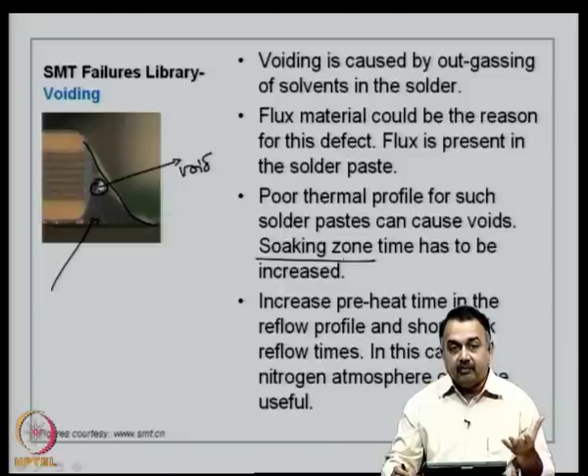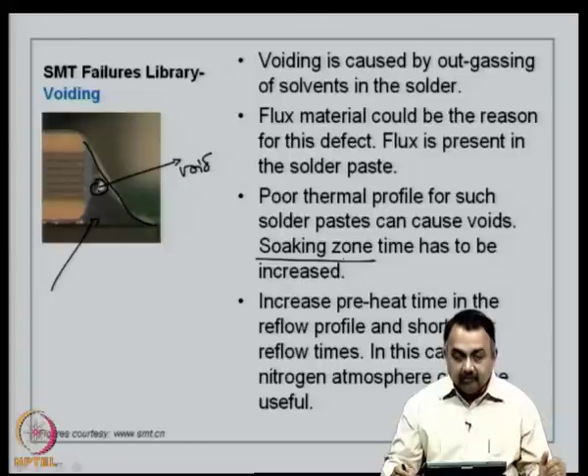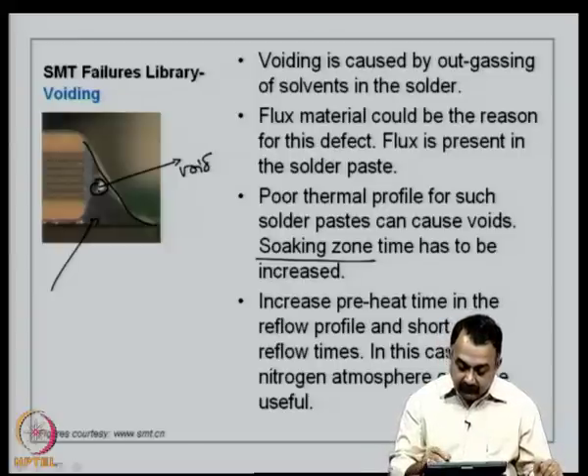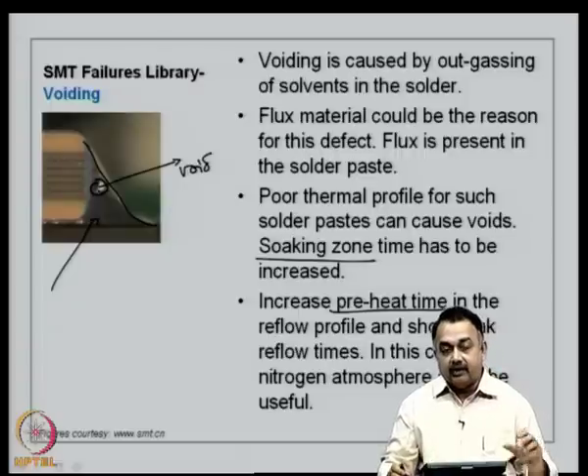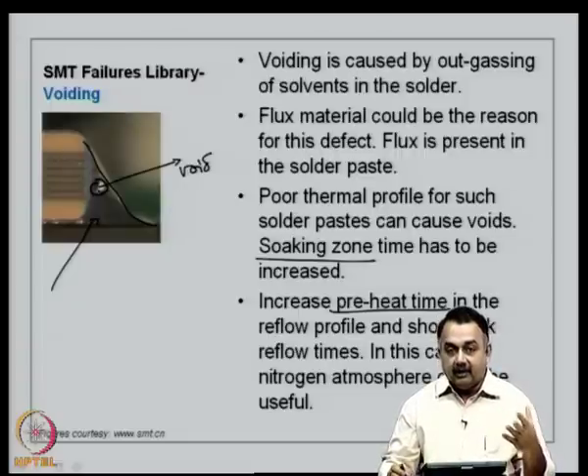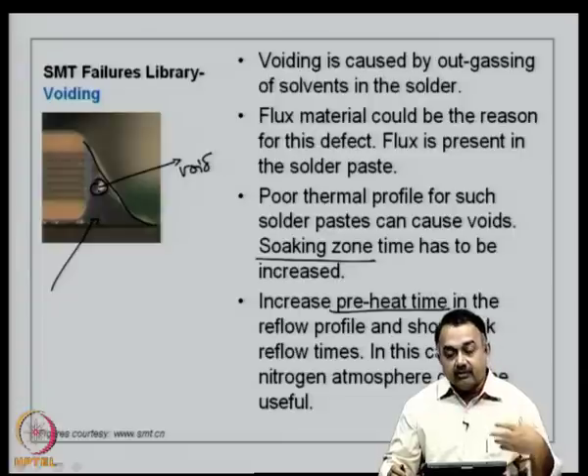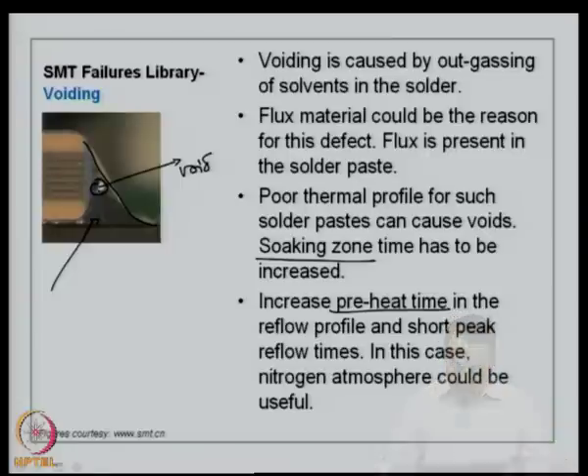So, you have to activate the board very slowly, or you can keep it activated for a longer time in the soaking zone before you go to a reflow zone. Also increase the preheat time of the board so that your copper pad and the substrate are nicely activated, and then it next goes into the soaking zone where the solder paste material and the flux material are activated gradually. So, in such cases if you think that air is a deterrent, you can probably work with nitrogen atmosphere so that you can control these kinds of issues.